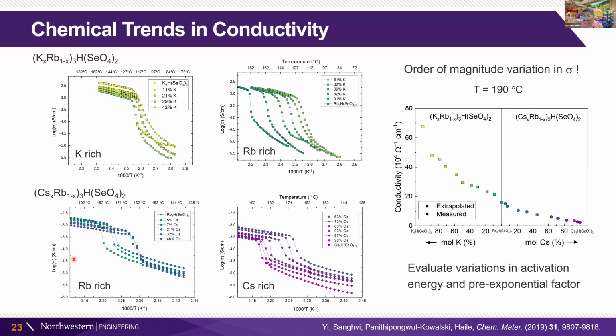An order of magnitude is pretty significant. So that's the cesium end is close to, maybe 5 times 10 to the negative 4th inverse ohm centimeters, whereas at the potassium end, we're above that, again an order of magnitude higher.